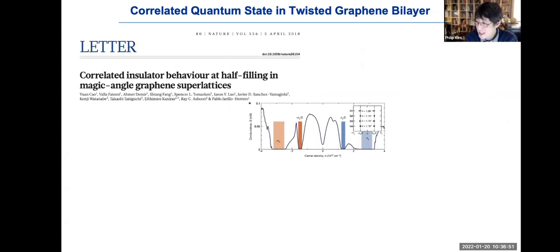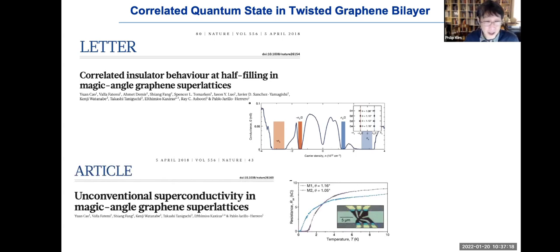But what is a rather exciting part is that quite recently, about 3 or 4 years ago now, right? The group led by Pablo Jarillo-Herrero at MIT discovered that if you tune this twisting angle in graphene to something like what they call the magic angle, right at the magic angle, suddenly graphene turns into an insulator, a so-called correlated insulator. More exciting is that if you dope this correlated insulator, they started to see that it developed superconductivity.